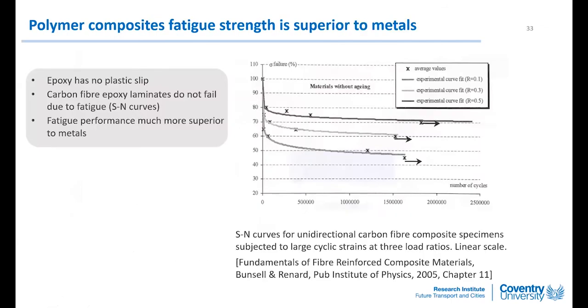The reason of this is because epoxy resin has no plastic slip line. So they don't have dislocation, cyclic slip, like metal. And the carbon fiber epoxy laminate, they do not fail due to fatigue. The S-N curve, again, from this book, is also flat. I just want to convince you. So the fatigue performance is much, much more superior to metals.